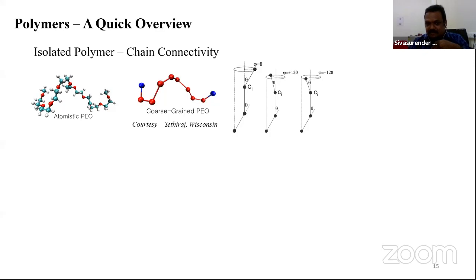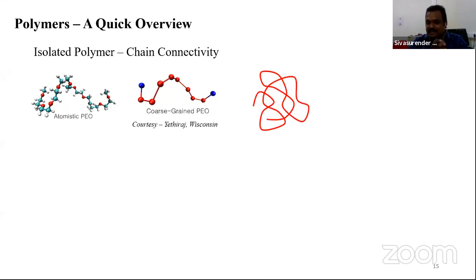However, the point of concern for polymer physics is that the number of monomers comprising these polymers is often too large, right? If I just have to give you some numbers, this number of monomers can go up to some 10,000, to lakhs, to tens of lakhs, for a single chain. So at that level, the polymer exhibits a different kind of global structure, where you no longer see the local interactions, and you can define the structure of the polymer by measuring a simple end-to-end distance of the polymer.